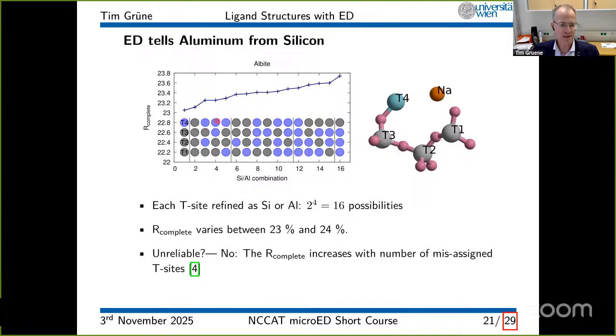So each block here has the same number of wrong atoms. Here you have 1 atom modeled wrongly. Here it's 2, here it's 3, and here again it's all 4 of them. And within each block, the R value is just getting worse and worse and worse. And even though the variation is only between 23 and 24%, this shows us that the R value itself, when you have the lowest R value, it means a good thing. It's not just noise that we're modeling here. We're actually having some information, and the information in the ED data is so sensitive that we can differentiate silicon from aluminum.